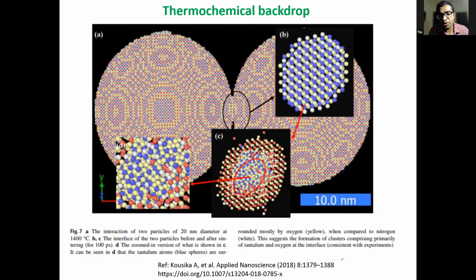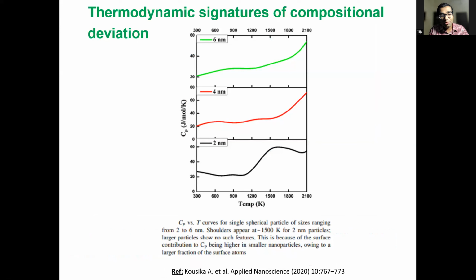And what we found was that in the nano regime, if you make these nanoparticles, you could potentially run into compositional instabilities, which of course we in one way or the other expect, but we are able to quantify these instabilities. Next, please. Now, the instabilities can be quantified in very many ways. One proxy way of quantifying it would be to look at something like specific heat as a function of temperature. And you would find that as you go further and further down in size and with respect to temperature, you start seeing additions to CP, which primarily indicate that there are some soft phonon modes that are being introduced into these particles, in particular on the surface.